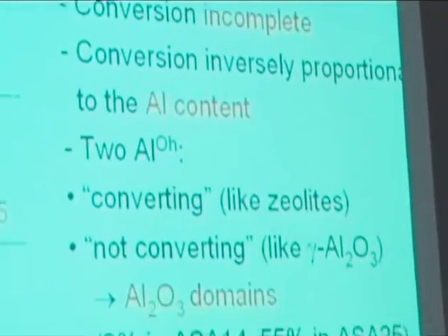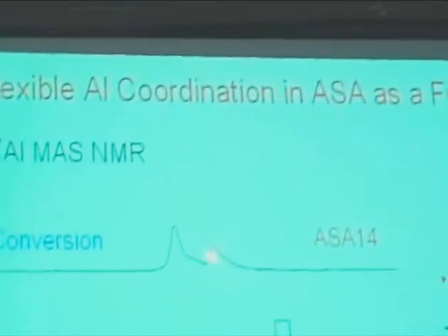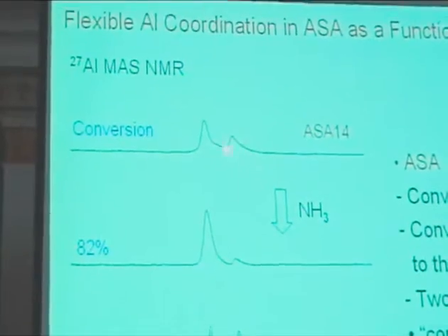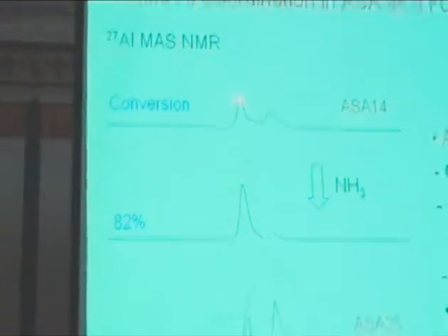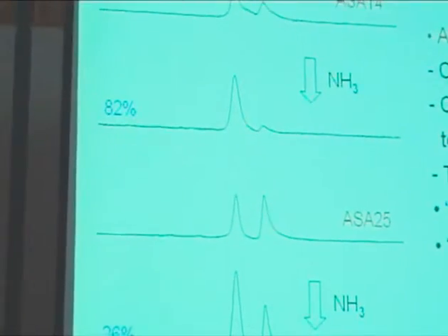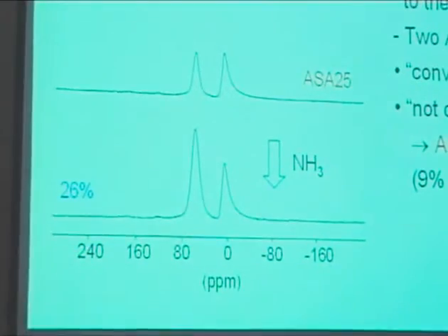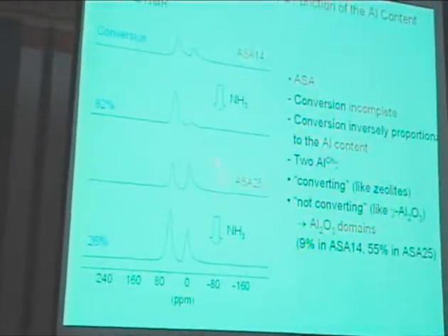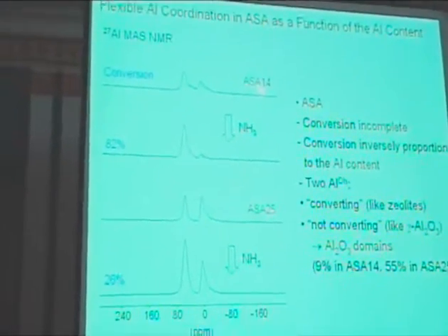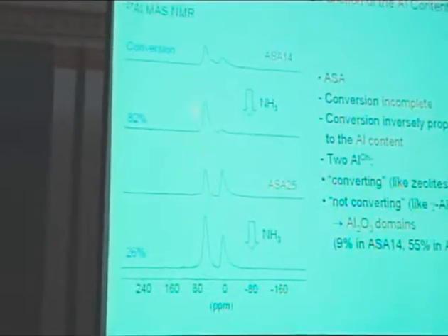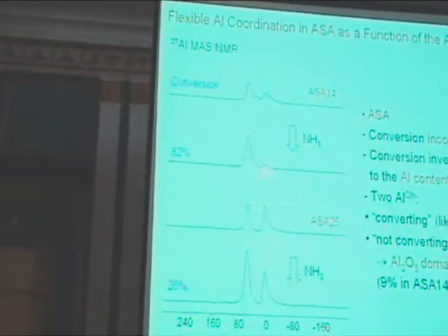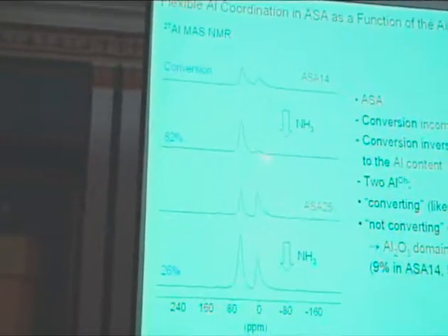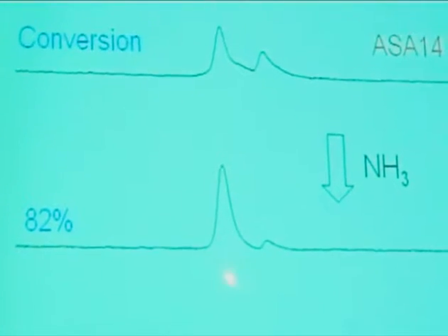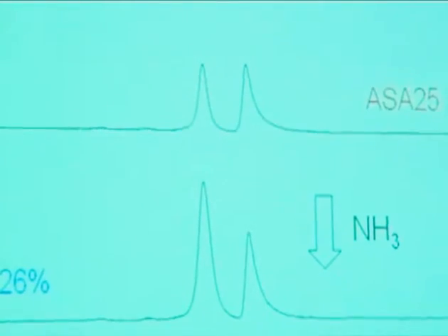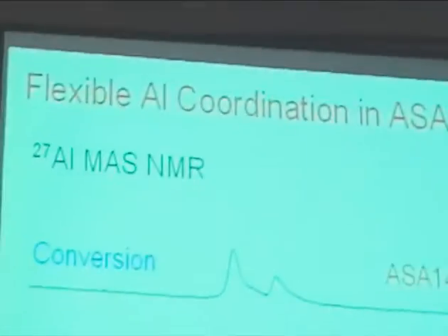So you can do the NMR, you can do similar things. For instance, here is an amorphous silica alumina. You can see also by ammonia you can do it. Even in the amorphous silica alumina, you have the octahedral peak at almost 0 ppm, this is aluminium NMR, and the one at about 60 for the tetrahedral. And you would have thought that that is the octahedral aluminium of the gamma alumina type, which you have in amorphous silica alumina. But you see, if you have only 14% aluminium content, most of your aluminium is really tetrahedral. Because even this can be brought to tetrahedral. You increase this, meaning that only a very little bit is really octahedral. And under the wet conditions, well, it's just hanging on there. It was tetrahedral, but it expands by taking up water, but it still belongs to the tetrahedral part.